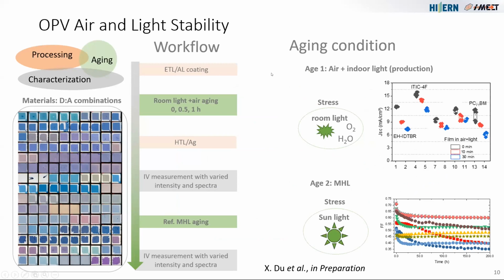One was basically to move the semi-finished cell with only the active layer, without the electrode, out into air for 30 minutes with indoor ambient light to see how it would change the performance if we processed in air. And then for another cell that was fabricated the same way, we kept everything inside the glove box and did a metal halide degradation test for 200 hours, where we degraded all the cells for 200 hours.